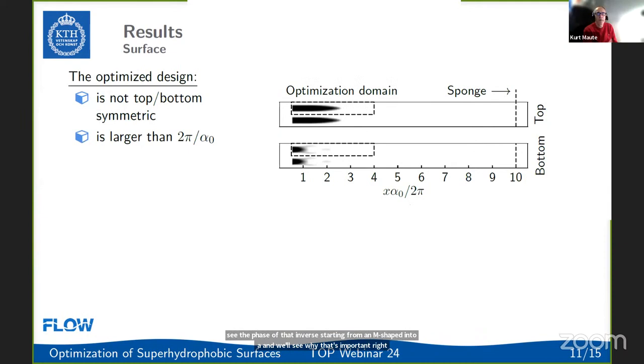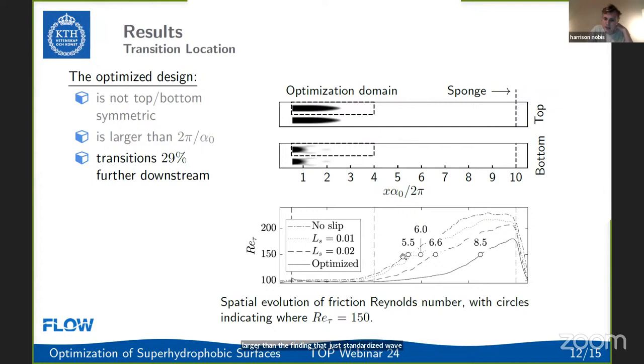So just to summarize, not symmetric on the top and bottom, and larger than the fundamental spanwise wave number. If we compare it to our reference cases, you can see the no slip case is the first one to transition. If we paint the whole surface with our least slippery material, that would be like coloring the whole thing in black, we get a slight improvement in transition location. If we use our most slippery material, we again get a slight improvement in transition location. But our optimized design actually transitions 29% further downstream than if we were to use just the slipperiest material. So that's a huge improvement.